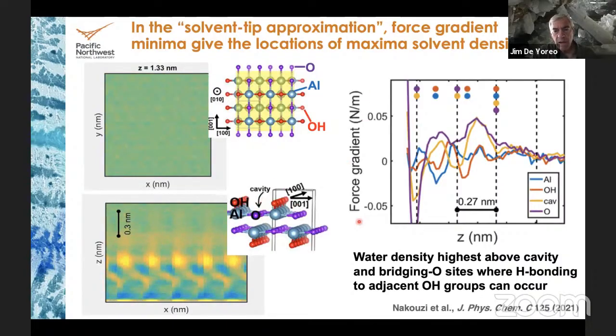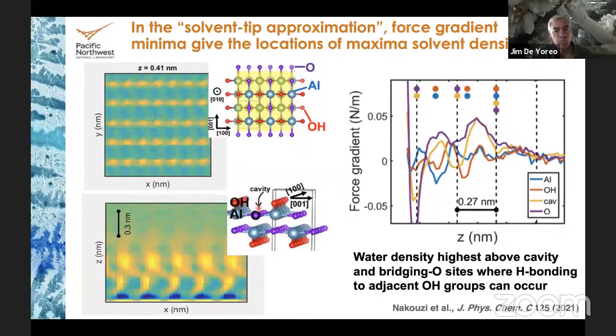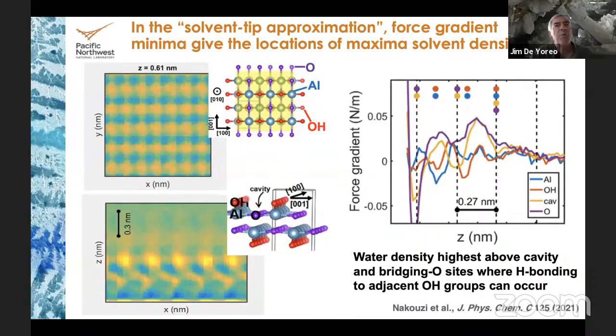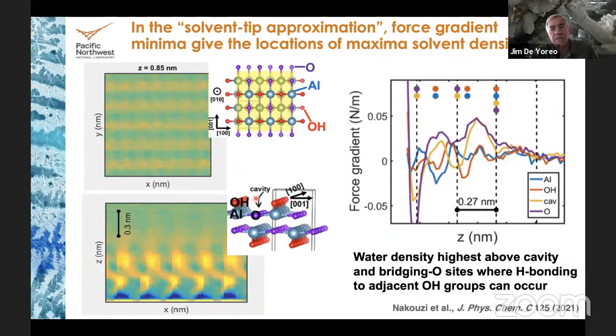If we plot the 1D force gradient curves, you can see where these minima and maxima are. And where the minima in force gradient are, so let's take the first hydration layer, they lie over the cavity sites and the oxygen sites. So that's along this row. And that is where the water can hydrogen bond to the OHs. So that makes a lot of sense, right?